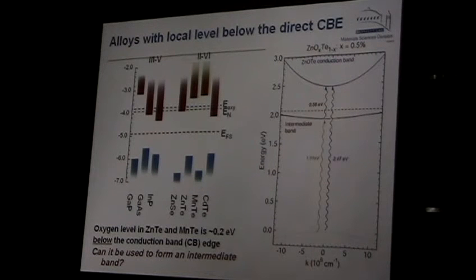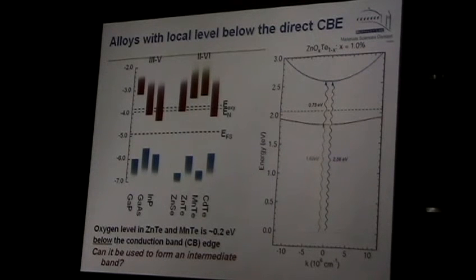Now we put more oxygen. Oxygen starts to interact with the conduction band, pushes the conduction band away, and broadens. The level becomes a narrow band. We put more oxygen, and it broadens even more. And we see now, if we have the Fermi energy here, we can have all three transitions: from valence band to conduction band, from valence band to intermediate level, and from intermediate level to conduction band. So we have something which looks like an intermediate band material. Finally, we can change the width of the band by the amount of oxygen we put in. Also, because of the interaction, we can control this energy distance by composition or by the amount of oxygen.